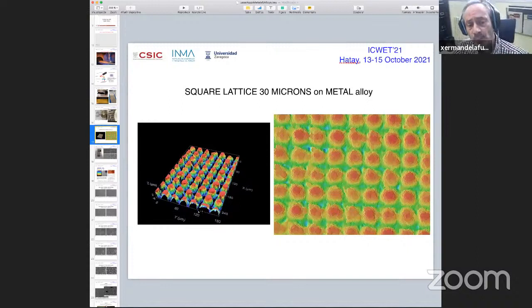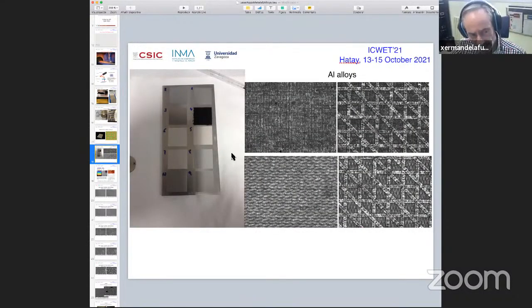And this is what you have. This is what you can do at larger scale with microns. You can do very well ordered arrays at different scales. Usually in micron scale is quite easy. And you can generate many combinations of micron scale structuring on the surface, as you can see here, very well ordered, long range. Although these are small samples, you can see the surface finish is quite different, and there's nothing added there. It's just the surface structuring that changes all these optical properties and other types of properties, as we will see on the metal.